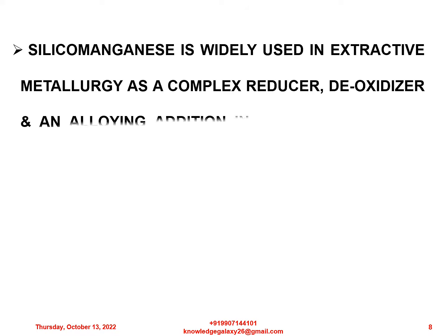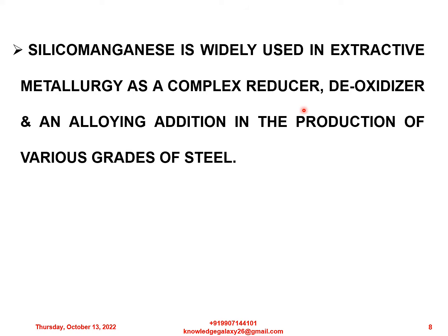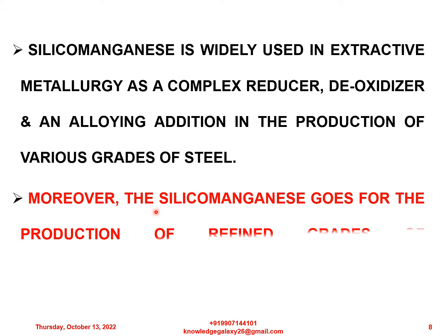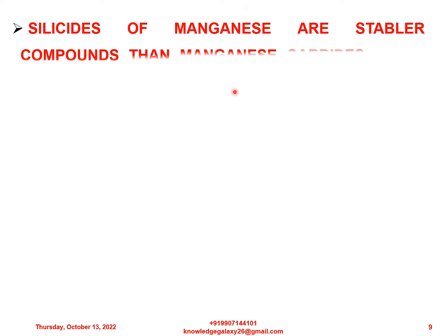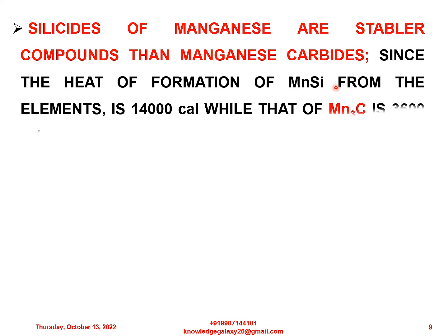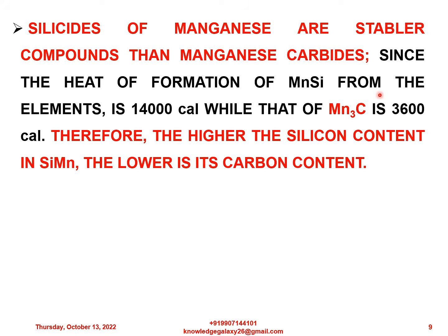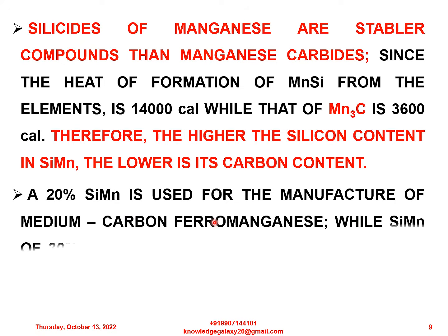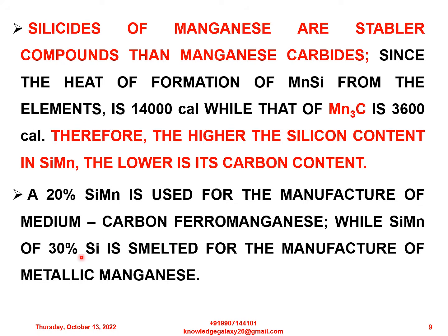To start with, silicomanganese is widely used in extractive metallurgy as a complex reducer, deoxidizer and an alloying addition in the production of various grades of steel. Moreover, silicomanganese goes for the production of refined grades of ferromanganese. Silicides of manganese are stabler compounds than manganese carbides, since the heat of formation of manganese silicide from the elements is 14,000 calories, while that of Mn3C, that is manganese carbide, is 3600 calories. Therefore, the higher the silicon content in silicomanganese, the lower is its carbon content. The 20% silicomanganese is used for the manufacture of medium carbon ferromanganese, while silicomanganese of 30% silicon is smelted for the manufacture of metallic manganese.